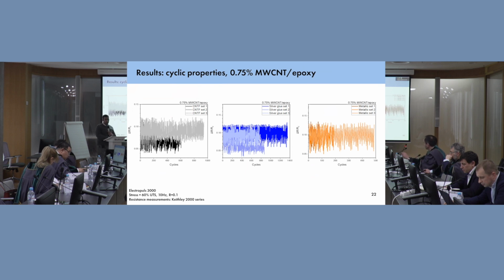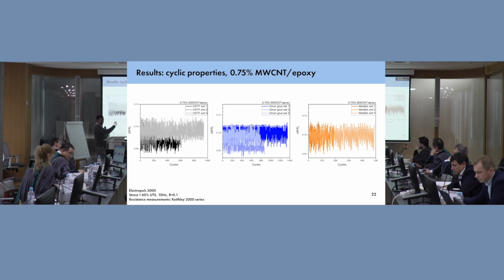Thank you very much for the question, Professor. So in this case, generally with cyclic testing, let me just go over it quickly. We put our sample in a machine which oscillates in one axis. In this case, because we had relatively stiff samples, there was sharp breakage. Beyond this point, we have some electrical response, but we cancel it. We cancel it when we present the data simply because for our CNTF samples, we did not have breakage in this gauge length where our CNTFs were. For the metallics, we had exact crack there, and it was only fair that we don't show the whole cycle simply because it broke at this point, and we need to normalize it.